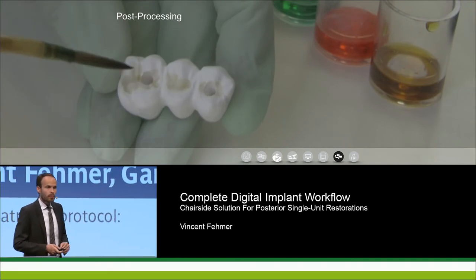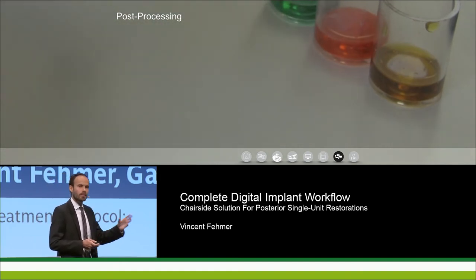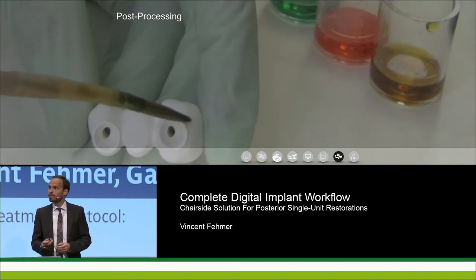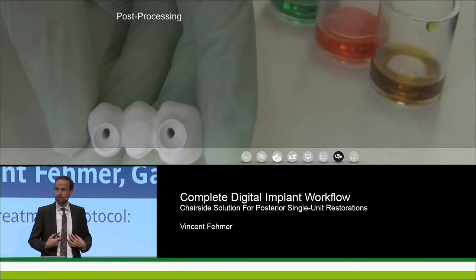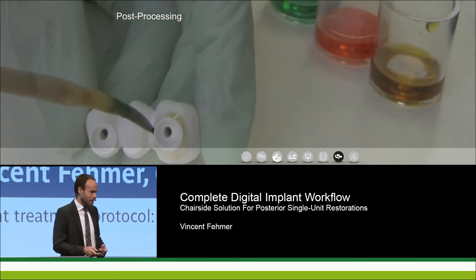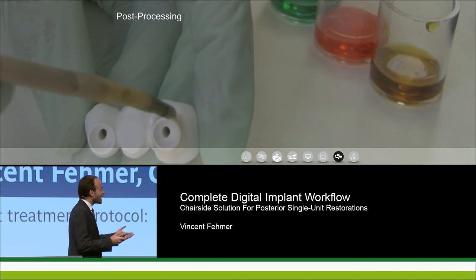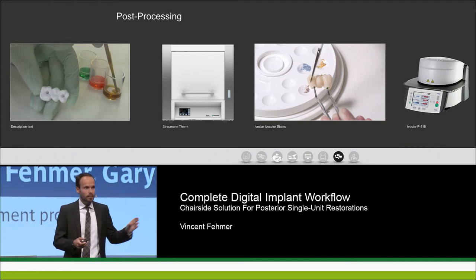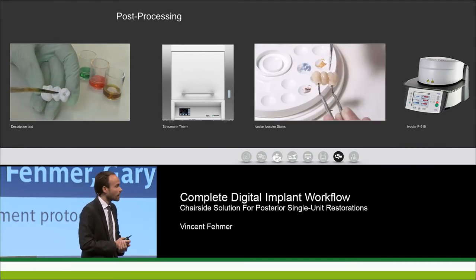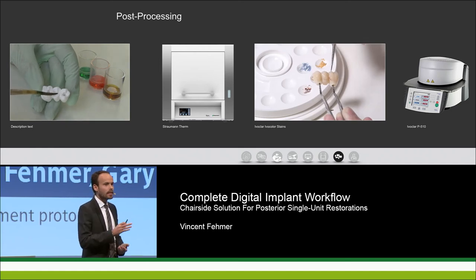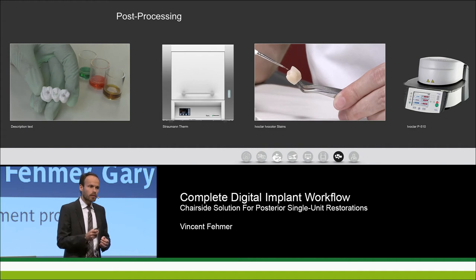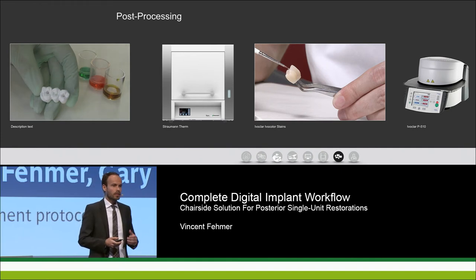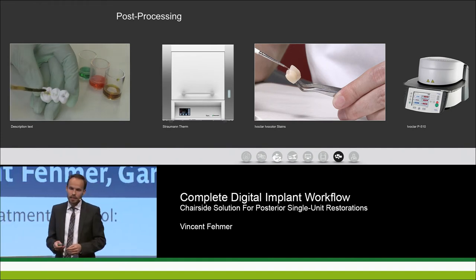Even with monolithic zirconia, it may not be the absolute final reconstruction — the dental technician is still needed. After production and sintering, there is a need for staining and glazing, adaptation of the surface, and superficial details. In the anteriors, a buccal veneering may still be appropriate. The dental technician's role evolves rather than disappears.